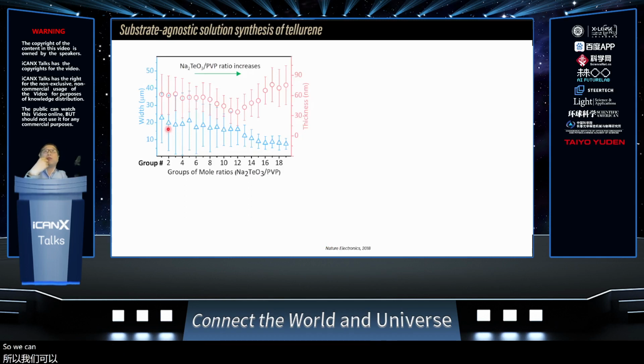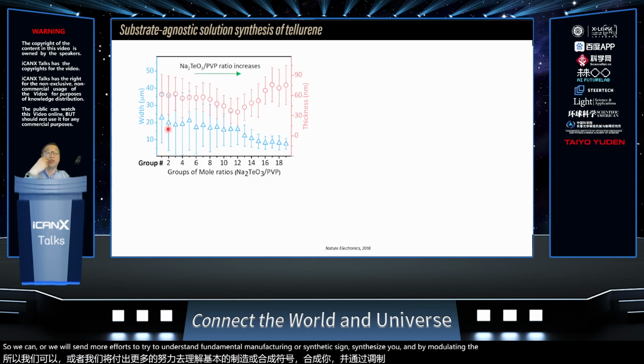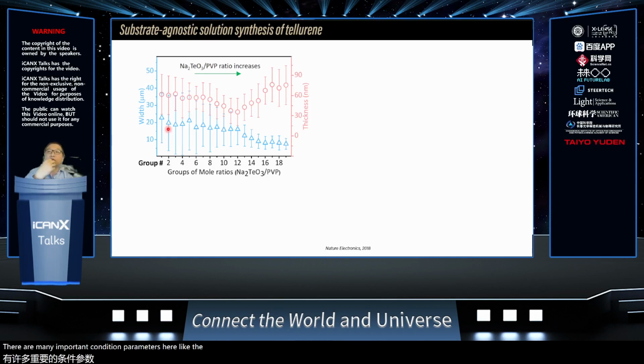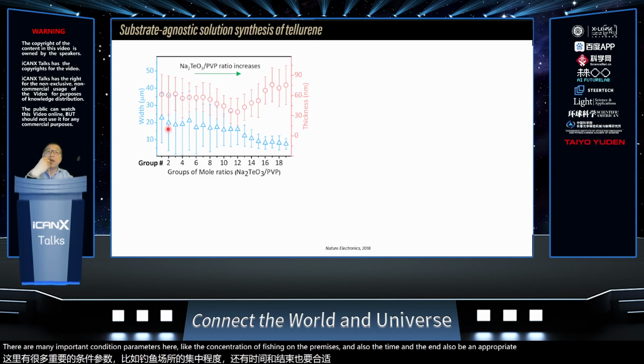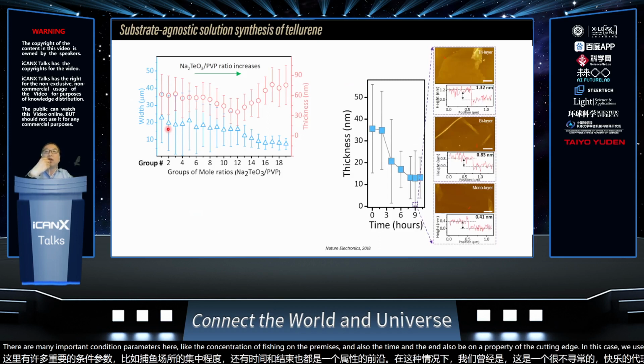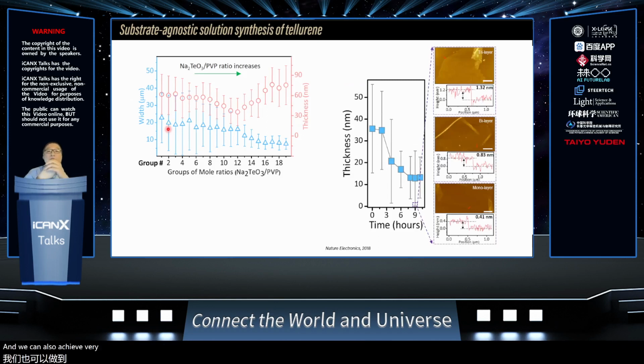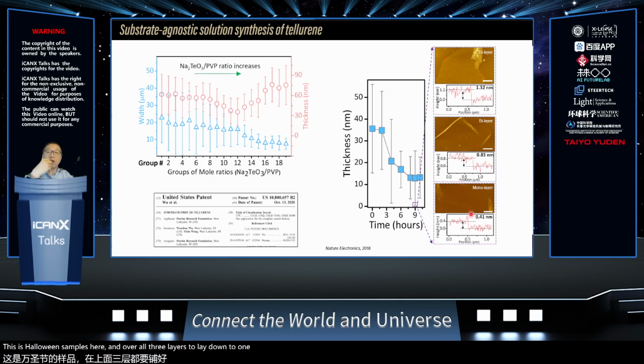We spent more effort to try to understand the fundamentals of the synthesis science here, by modulating the synthesis parameters. There are many important parameters, like the concentration of the precursors, the time, and the property of the capping agent. In this case, we use PVP, which is a very common capping agent for chemical synthesis. We can also achieve very good control over the thickness of the synthetic tellurene samples, from 3 layers, 2 layers, down to 1 layer. And we were lucky to get a US patent for this technology.